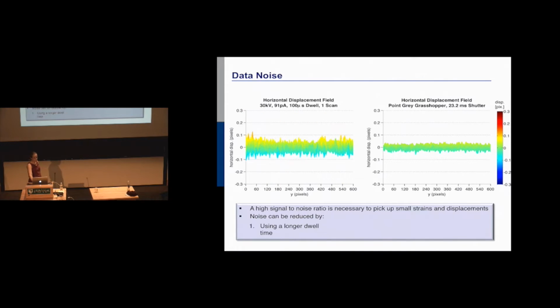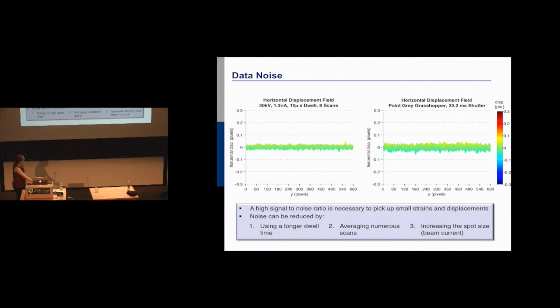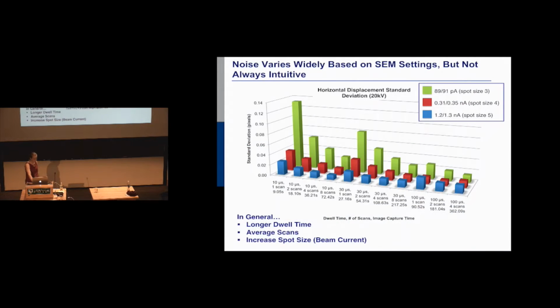In general, you can use a longer dwell time, you can average scans, and you can increase the spot size. However, nothing comes without a price. If you use a longer dwell time, you're spending longer on your scan. You can induce more damage, you can induce more contamination, which can induce more drift, you can have stress relaxation, all sorts of things. So it's a balance.